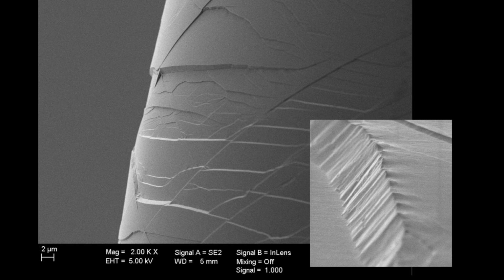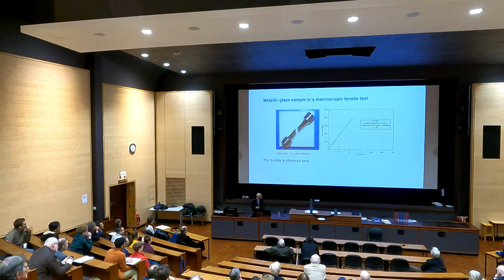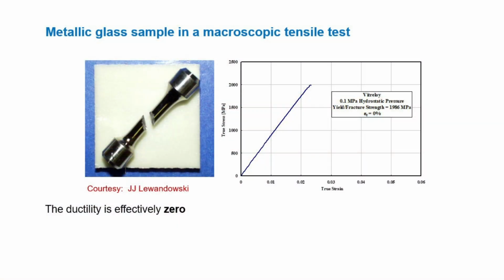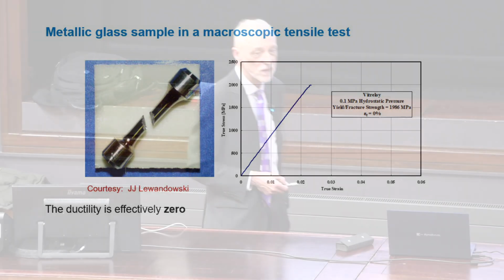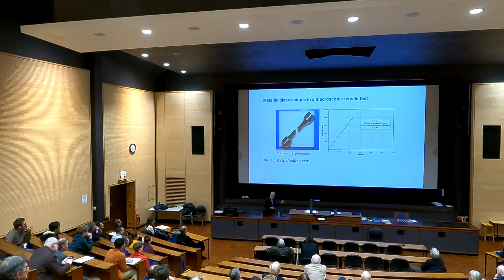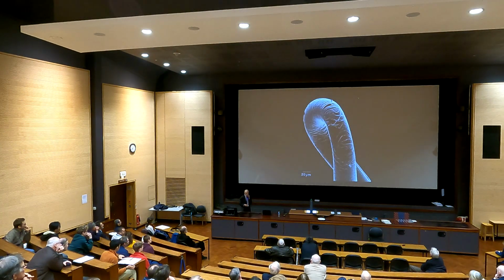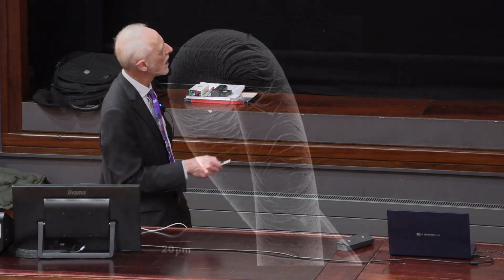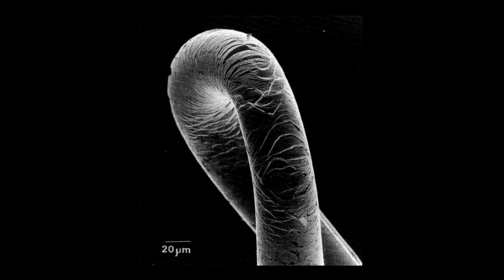These shear bands are a remarkable phenomena in their own right. They're utterly clean, not a hint of a crack anywhere. But when the material is in tension, they spread across the cross-section, and you get, after the elastic region ends, you just get fracture. So our ductility is not the 30% of the copper bar, it is 0. And that would generally be thought to be bad news. To give you a sense of how remarkable they are, this is a bent metallic glass wire, lots of these shear bands. They're, of course, very unsightly, which is one problem.